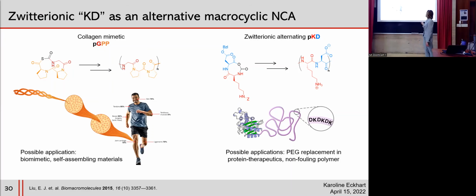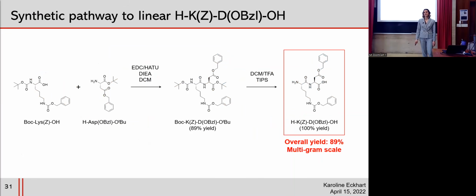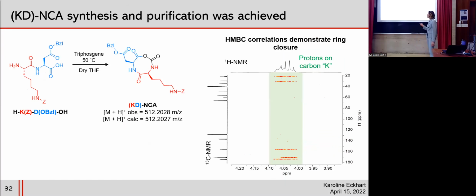And we specifically chose KD as our amino acids because this material would be a zwitterionic copolypeptide, which could be a useful replacement for PEG, or could be used to make a non-fouling surface. So we prepared our KD dimer, and this was a 2-step synthesis with an overall yield of 89%. We love that. And we could make it on a multi-gram scale, so this enabled us to get many tries in optimizing the synthesis of KD-NCA. We were able to prepare KD-NCA and confirm its synthesis by high-resolution mass spec and heteronuclear multiple bond correlation.